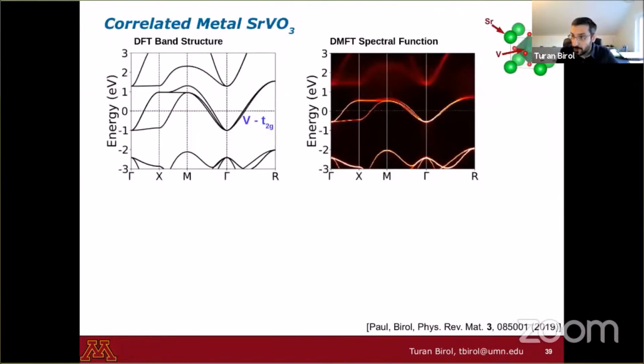So this is what you get from DFT plus DMFT. So from DFT on the left and DFT plus DMFT on the right for strontium vanadate, this perovskite. The band structure in DFT is well defined. There are these perfectly sharp bands, as I said, whereas in DMFT, there are two things that are different. One, there's a finite lifetime of these bands, so things become fuzzy. And if this was a more correlated material like a Mott insulator, then you wouldn't even see the bands, you would just see a cloud of electronic states. But the other thing that's different is the width of these bands. In DMFT, you end up with bands that are just about half as wide as they are in DFT in this particular system. The ratio we denote by Z, this is the quasi-particle residue.